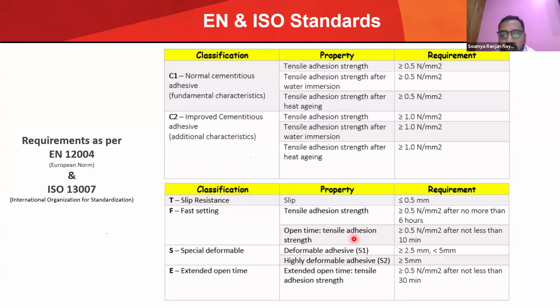Okay, so deformability, as I told you previously, as I showed you in the picture also. S1 means, as also mentioned on tile adhesive bags, this is S1. S1 means it has deformability. It can bend up to 2.5 mm to 5 mm. S2 means high deformability. It can bend more than 5 mm. Extended open time means the general open time is like 30 minutes. Okay, extended open time means it will give an open time of more than 30 minutes.